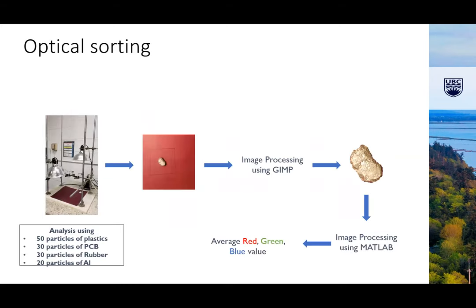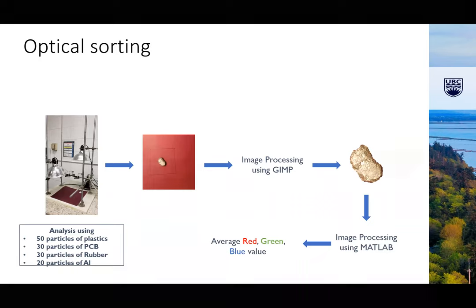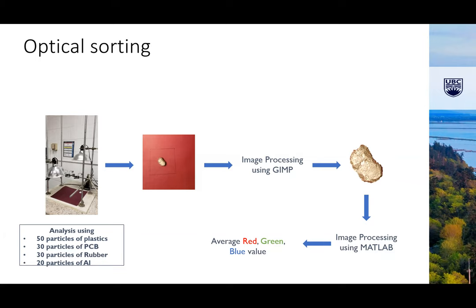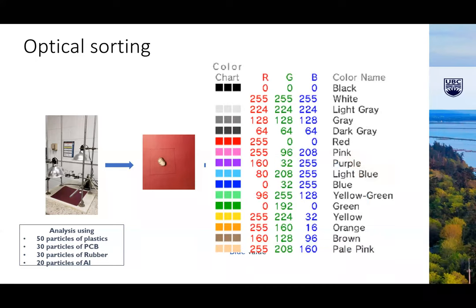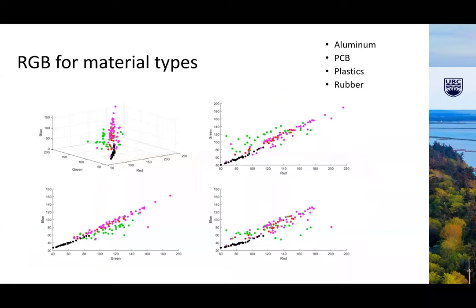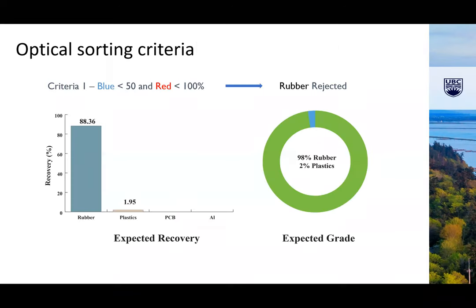Another opportunity, when we are at this sort of coarser size reduction that we allowed for coarser particles to be processed, is optical sorting, where we can look at each piece because the color would also be distinguished. So we used optical sorting. The particles of plastic, PCB, rubber, and aluminum were analyzed. And the software was designed to recognize these. Then we correlated blue, green, red, and various opportunities to correlate. And what we found was that there were criteria that we could very easily separate rubber at